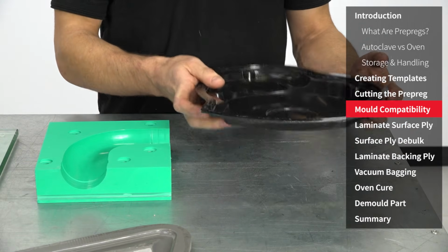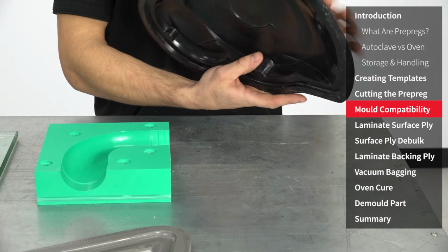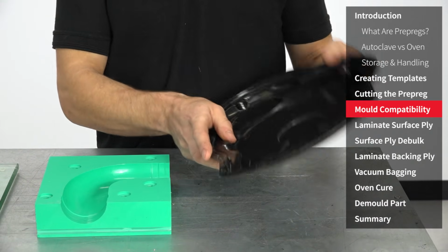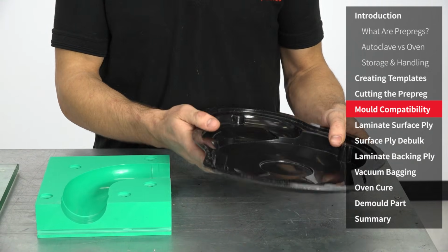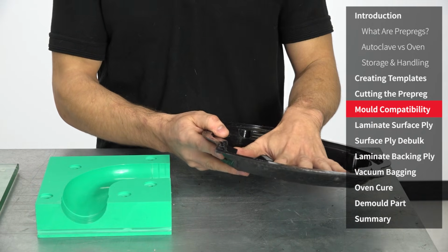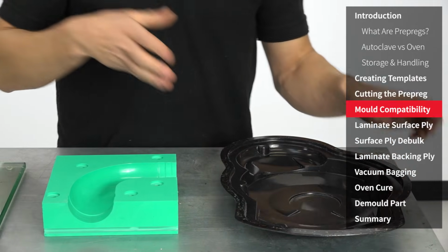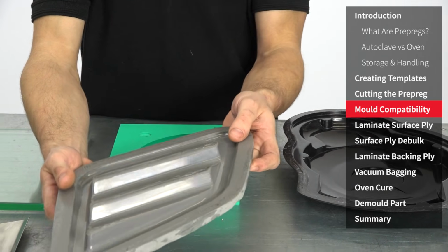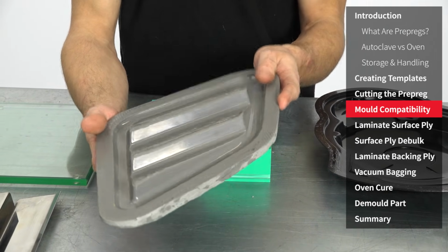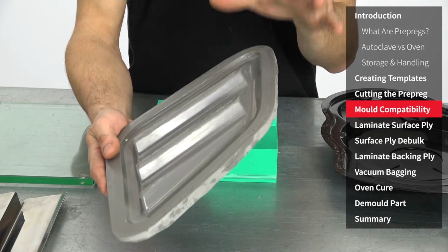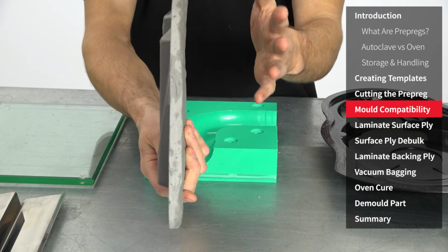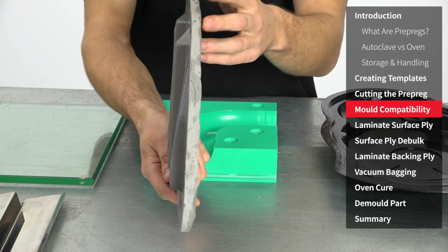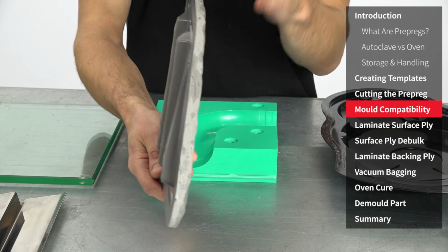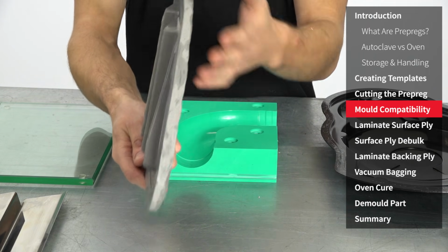The mould that we're using in this video is the pre-preg mould that we made in a previous video in this series. It's got a maximum service temperature of 135 degrees C and is fully compatible with the XPREG. Another very common mould material is high temperature epoxy, which is hand laminated. So this is made using a wet gel coat, and then this has been backed up with a high temperature laminating paste. But equally, that could be done with a high temperature epoxy resin and glass fibre or carbon fibre.